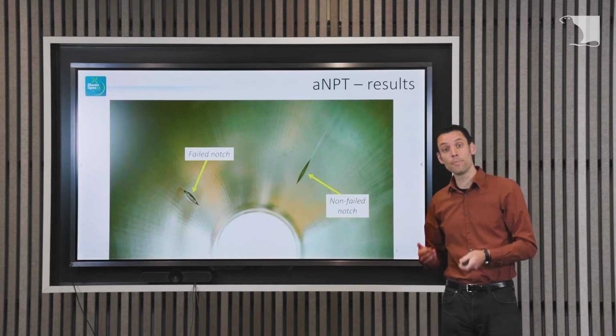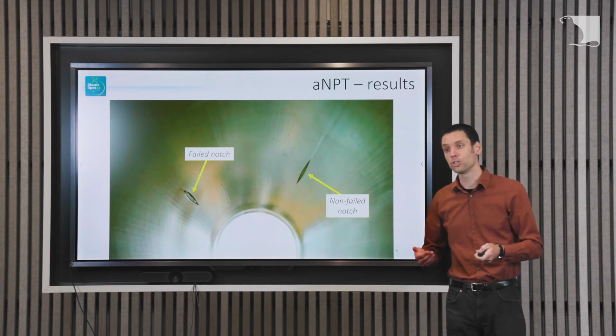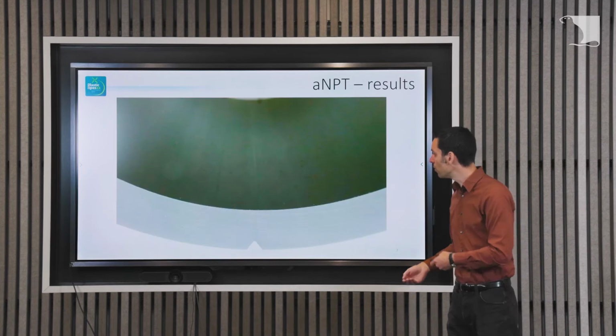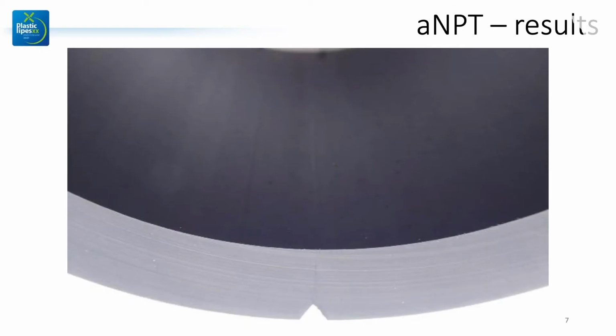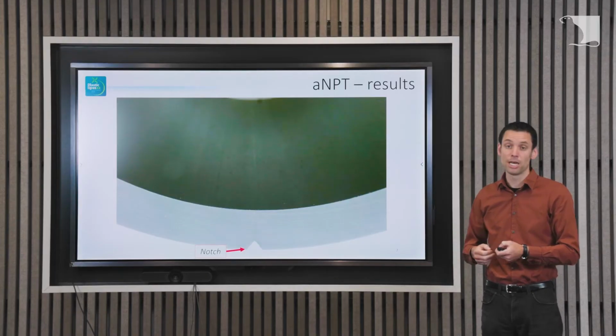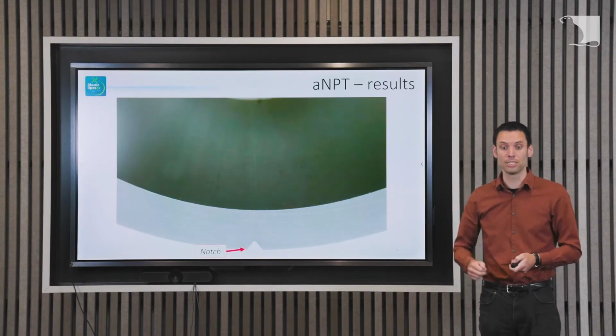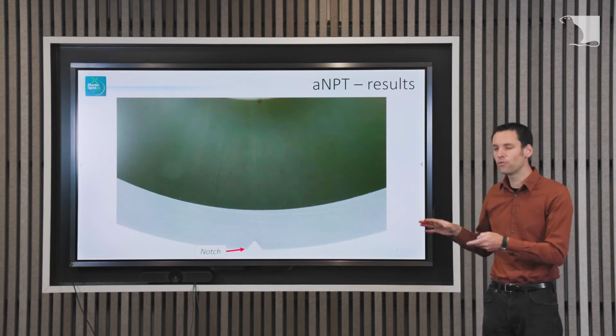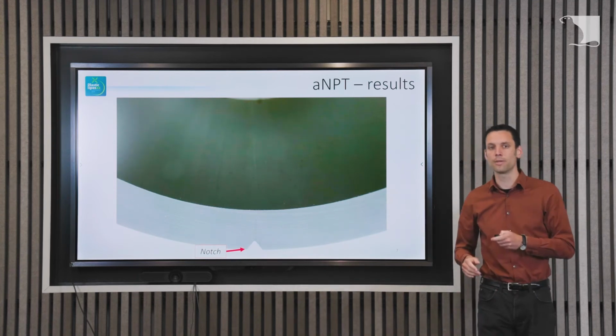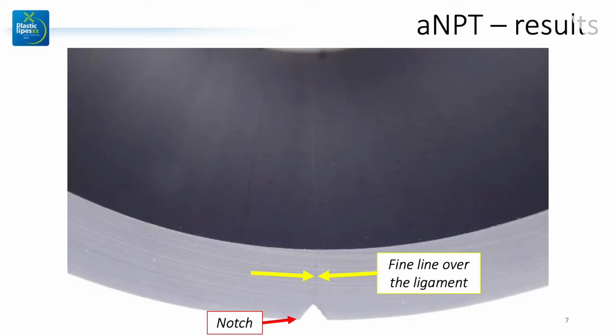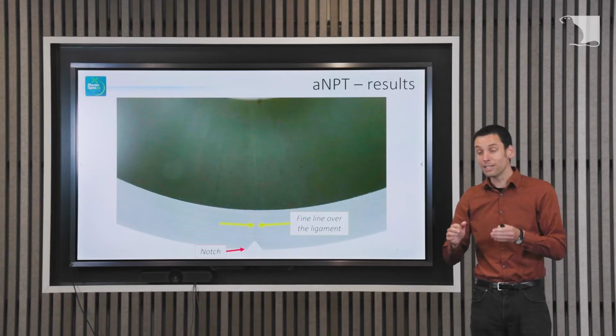What we did was we made a cross-section of those notches to see what is actually happening here. Here you see that pipe wall thickness. So you see just the pipe wall and on the bottom side here is the notch. And what we see further on, well, we don't see anything on the inner pipe wall. So this was one of those 2 notches that didn't crack completely through, or we didn't see on the inner side wall. But what's very interesting, and it's very difficult to see, but you can see it quite clearly on a microscope, is that there's actually a fine line over the ligament, starting from the notch to the inner pipe wall. And this is actually quite strange.